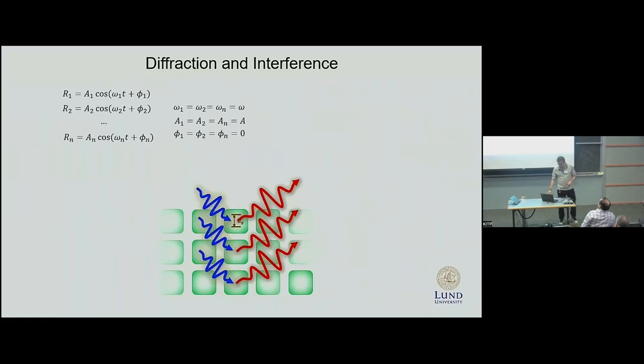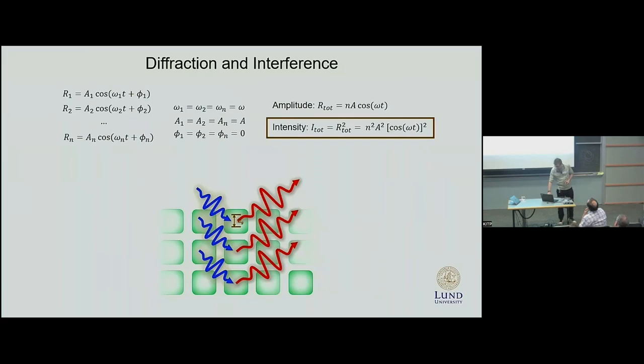Now let's imagine that all of them are exactly identical - if they are artificial atoms, so all atoms, let's say, are identical. In this case, all the frequencies will be identical, amplitudes, and there will be no phase shift. So the total amplitude will simply be a sum of the individual amplitudes, and the intensity, which is a square of the amplitude, will be proportional to n squared, the square of the number of emitting particles.